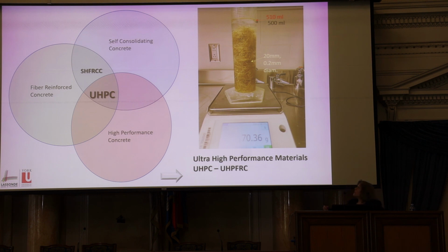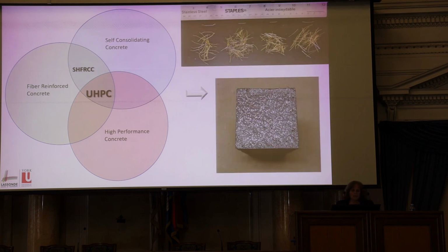They contain fibers. For instance, this cylinder gives you the volume that is taken by half a liter of water. The lower line, the black line where it says 500 ml, gives you half a liter of water. And the red line, which is just a fine portion higher, is what happens when you add 2% of the volume of the fiber. So you see lots of fibers, but they are only 2% of the volume of the material. What kinds of fibers are these? They are very fine fibers. Their typical length is about 13 to 20 millimeters. Their diameter is a fifth of a millimeter, very fine. And here is a concrete that has been reinforced with these fibers.